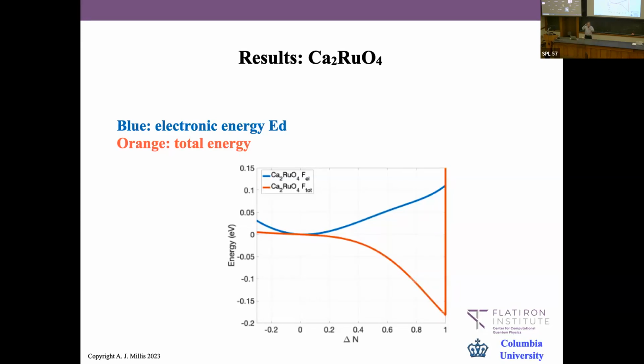No, it's simple. If you have a big gap, then there's a strong kinematic barrier, because if you recombine two electrons, you liberate a lot of energy and it has to go somewhere, right? And because the gap is very big compared to a phonon frequency, you need some kind of multi-phonon process to do it, or multi-magnon if you have that. So there's a kinetic barrier to relaxing across the gap just because you have to find somewhere to put the energy that's released. That's why it's slow. Because there's not enough other electronic states at high energy.